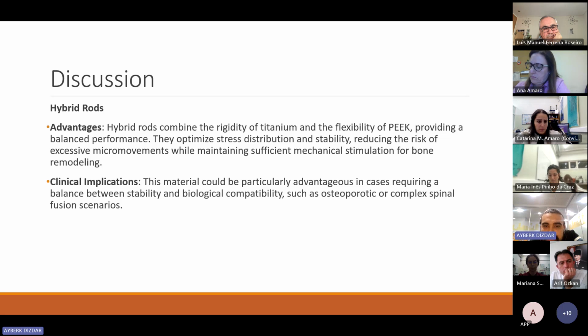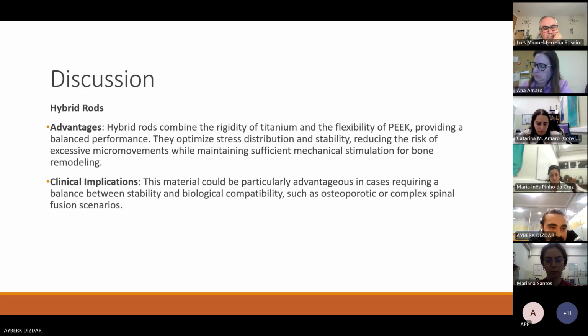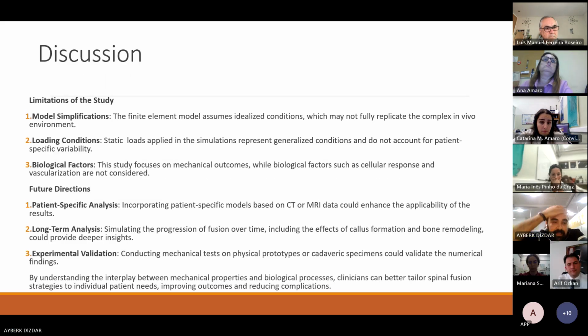Hybrid rods combine the rigidity of titanium alloy and the flexibility of PEEK, providing a balanced performance. They optimize stress distribution and stability, reducing the risk of excessive micromovements while maintaining efficient mechanical stimulation for bone. Clinical implications: this material could be particularly advantageous in cases requiring a balance between stability and biological compatibility, such as osteoporotic or complex spinal fusion scenarios.